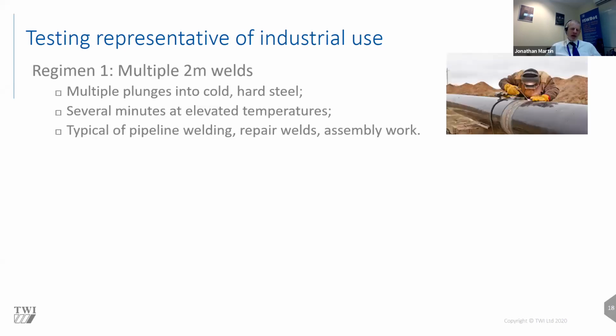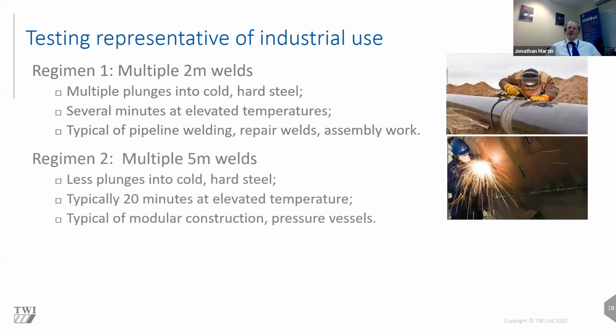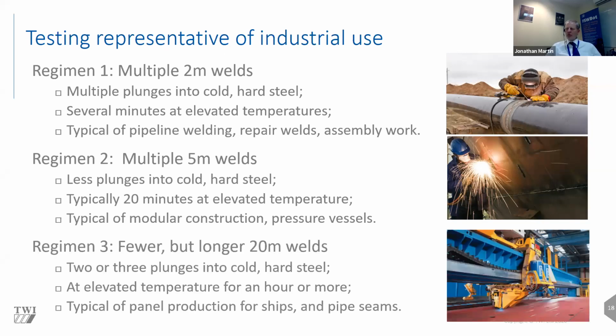So we set about doing a testing regime on these tools. In order to develop the testing regime, we need to decide what sort of applications these tools are going to be used for. So as Mike was saying, it's a very harsh environment for these tools. They're sitting at elevated temperatures for many minutes, depending on the application. If you're looking at pipeline welding, you would have multiple plunges and short duration welds, through to perhaps applications in the construction industry, where the welds will be slightly longer and therefore the plunge cycles will be less, leading through to really long welds used perhaps for panel building, for ships, etc. And these welds may be 20 meters long, and therefore the tool in these cases will need to sit at these elevated temperatures for over an hour.